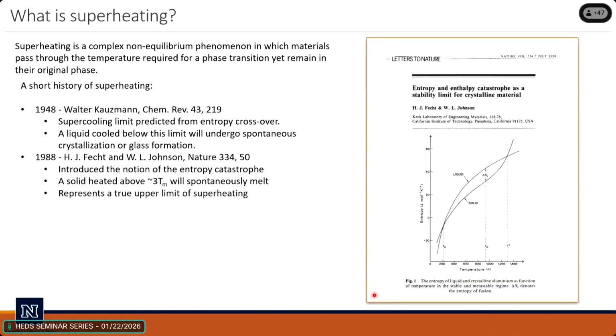30 years later, these two other scientists, Fecht and Johnson, wrote this paper where they just did the same thing but upwards. I don't know why it took 30 years for someone to say, oh, let's just go upwards in temperature. But they did the same thing. They just took these entropy curves and they went upwards, and they crossed at 3 times the melt temperature. So they said that you can never, ever heat something up beyond 3 times the melt temperature. That is the ultimate limit of superheating, 3 times the melt temperature.